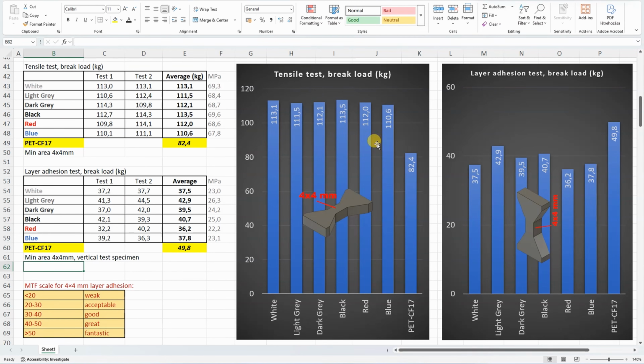Tensile test, very constant and strong values, bigger than carbon fiber version. Now with the layer adhesion, here you can see my ratings for this kind of test object, and in this case the carbon fiber version was stronger compared to the glass fiber version, but this is very good too.